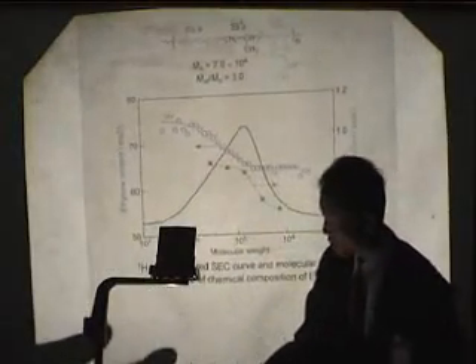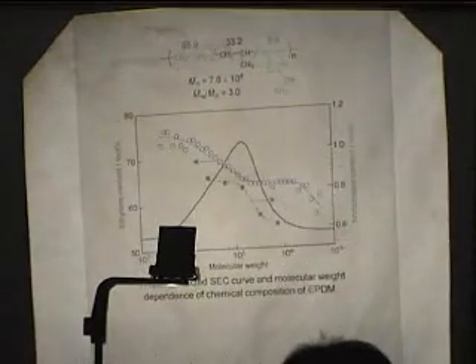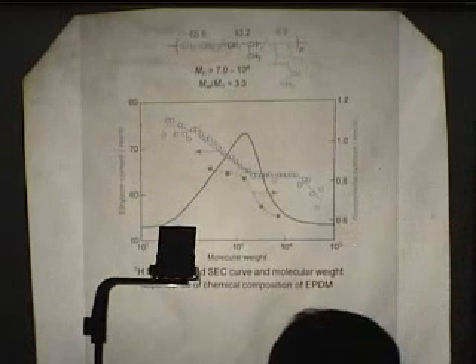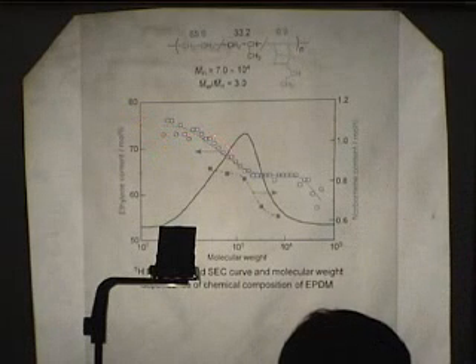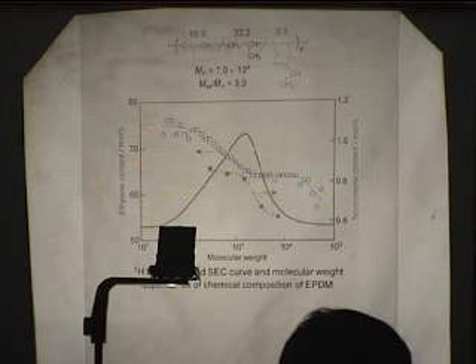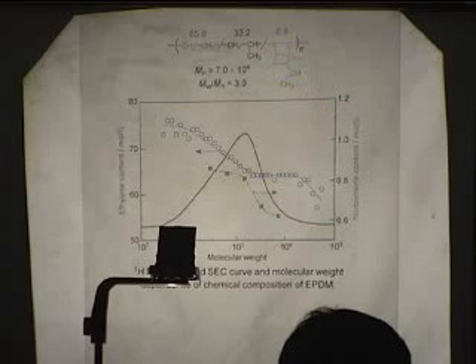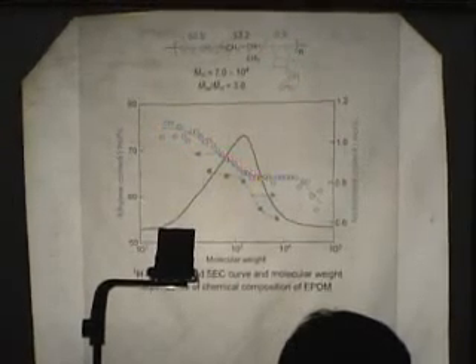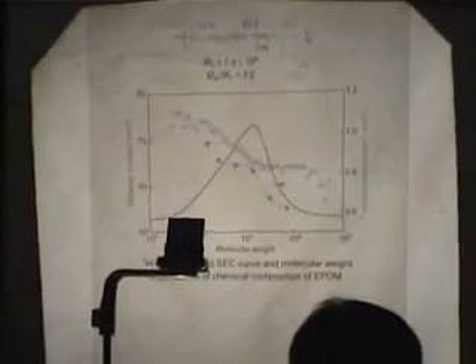This illustrates SEC-NMR analysis of an EPDM sample. Using continuous flow SEC, you can determine the ethylene content as a function of molecular weight. And using the stop-and-flow SEC, you can also determine the small amount of diene as a function of molecular weight. As you see here, the ethylene content decreases with decreasing molecular weight, and the diene has the same tendency. This can be related to the polymerization mechanism.